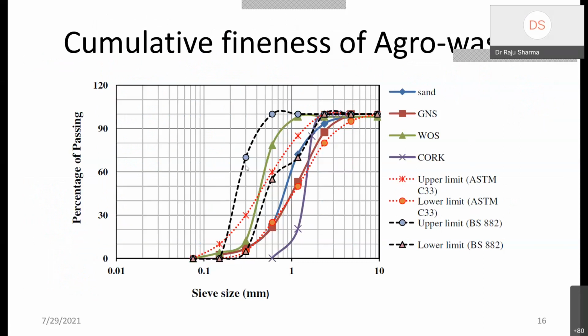concrete, where you can see that the sand is lying in the range of the upper limit of ASTM C33 and the lower limit of ASTM C33. And you can compare this range with your particular aggregate, with the fineness code in India also, and you can make this kind of boundaries with your particular sand or any fine aggregate which you are using as a replacement for the sand. And actually it gives a good presentation in your paper when you are submitting to the journal.